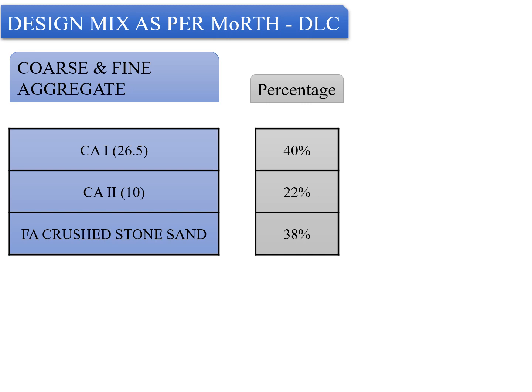So what is happening is, by varying the proportions of Ca1, Ca2 and fine aggregate, we try to match the theoretical combination of these aggregates in order to achieve the required gradation given in Table 600.1. Under this process, if you add 40% of Ca1, 22% of Ca2 and 38% of fine aggregate, your mix is able to satisfy the required grading requirement.